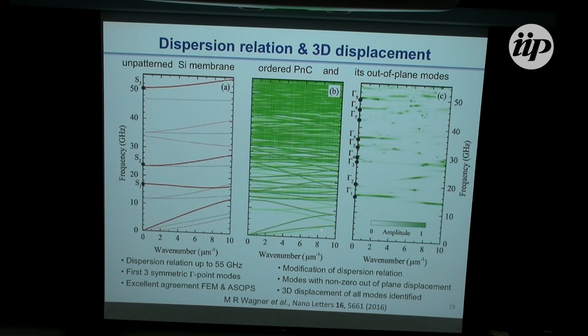The ordered phononic crystal also has a very well described dispersion relation, but you see that all the frequencies have come down. And the out-of-plane modes have intensities that vary. So this is higher amplitude, and then they lose the amplitude, some recover it, etc. But all these peaks at zero wave number are explained and ascribed as per the previous measurements.